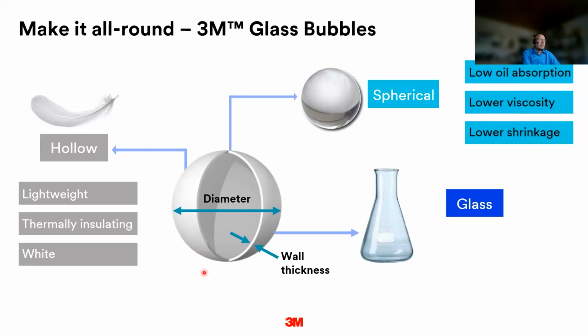Then their bubbles are perfectly round spheres, which means they have a low specific surface area, which means low oil absorption. And that means at a constant volume concentration, we have a lower viscosity, which on the other hand allows us to formulate with pretty high solid contents in terms of volumes. So we can formulate for very low shrinkage.